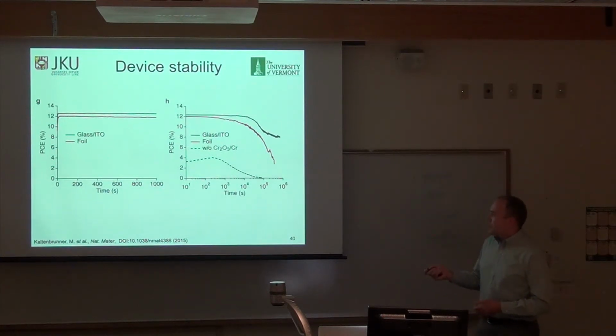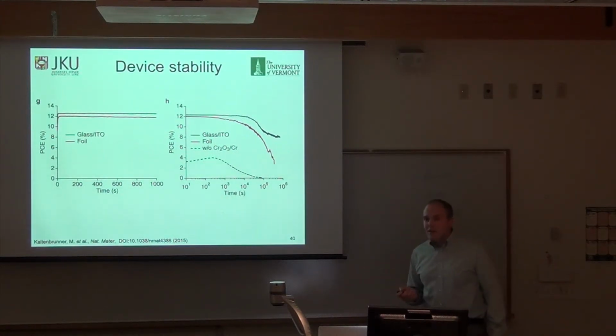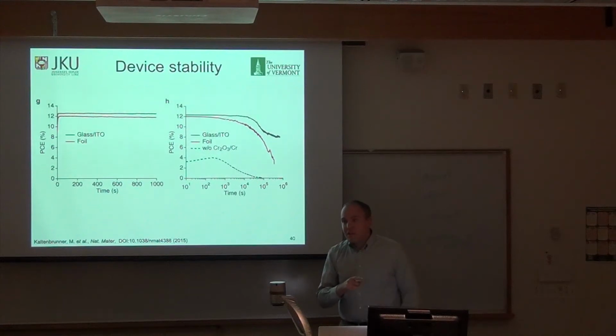We show here out to 1,000 seconds, which isn't so long, but you can see that it's stable at around 12% efficiency. The reason we had to do this is because within the perovskite community, there's a big discussion about whether you should sweep forward or backwards, because perovskites exhibit hysteresis since those dipoles can flip. This is a big source of debate, but for solar cells, you don't want to be sweeping when you're using them. You want to just put them on a load and let them generate power.